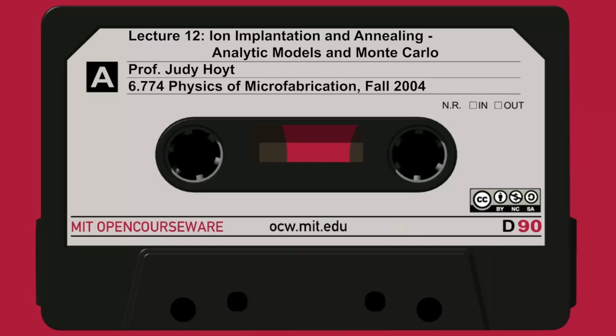So the things you need to remember are that ion implantation is a random process. A whole bunch of ions come in, and they randomly hit various things and lose energy and end up in some distribution. So it's a statistical type of process. The ions are pretty high in energy. We're talking about 1 kilovolt at the lowest, probably, up to maybe a megavolt. That's the range of energies, believe it or not, that people use in making modern devices. They can even get as high as a megavolt.